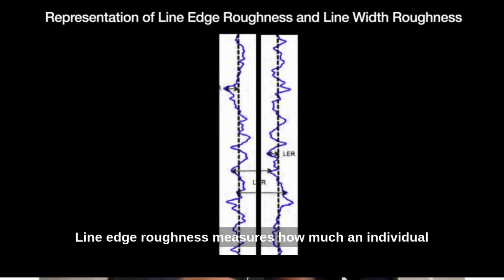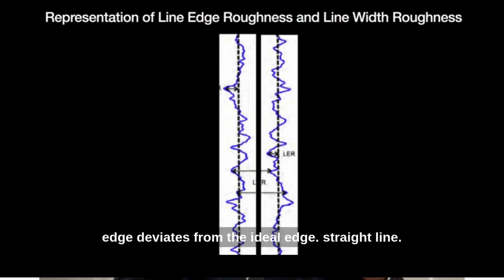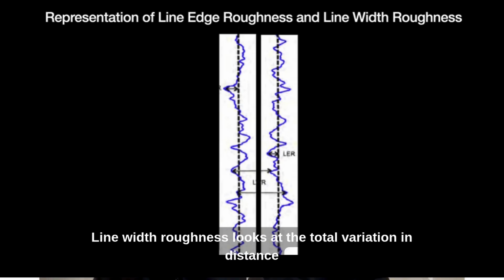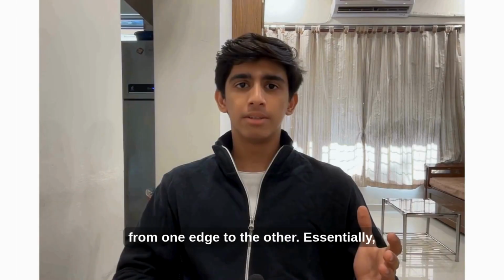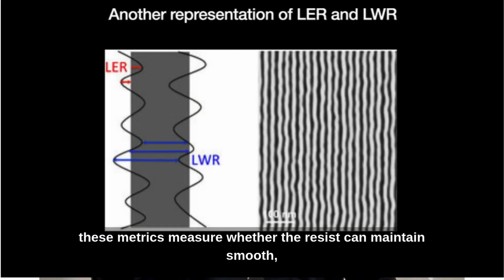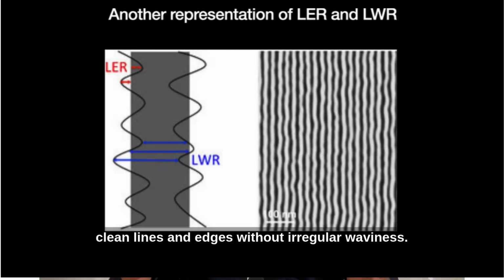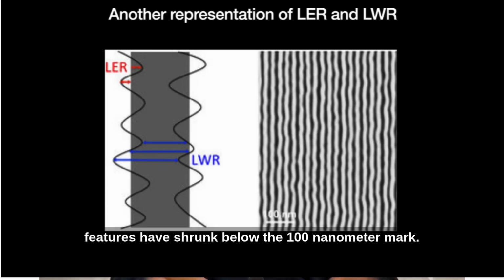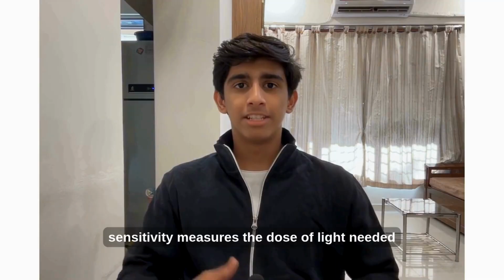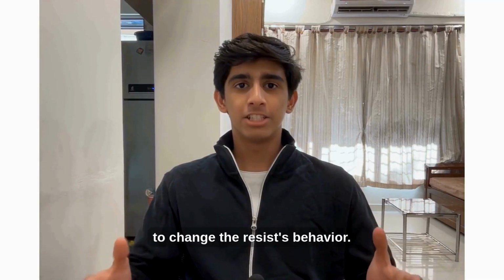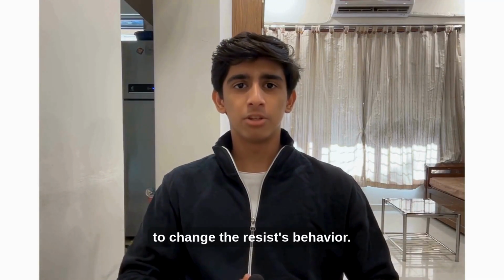Line edge roughness measures how much an individual edge deviates from the ideal straight line. Line width roughness looks at the total variation in distance from one edge to the other. Essentially, these metrics measure whether the resist can maintain smooth, clean lines and edges without irregular waviness. This has become increasingly critical as device features have shrunk below the 100 nanometer mark. Finally, sensitivity measures the dose of light needed to change the resist's behavior.